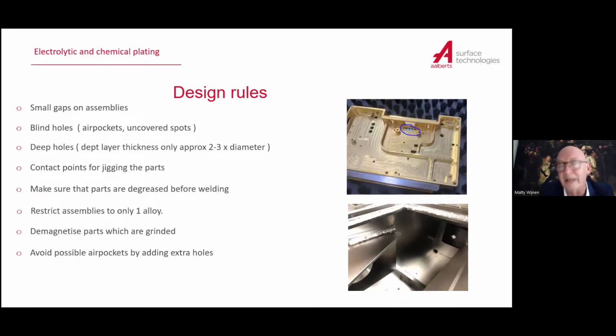you will have no plating, or you will have corrosion afterwards. When you use stainless steel, you can have corrosion in between, like pit corrosion, a special corrosion in between those parts. So that's very important. Better weld the parts or leave a space so that fluid solution can run in between. It doesn't have to be a centimeter or something like that, but a millimeter or two will give enough renewal of the fluid. Blind holes, also something.